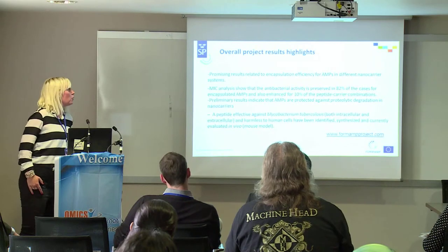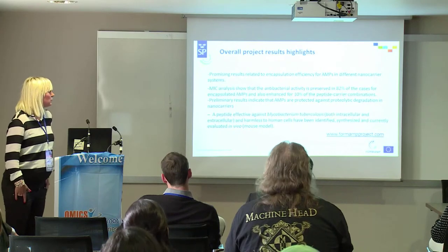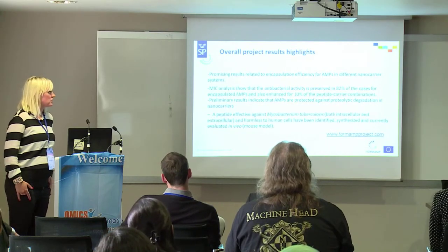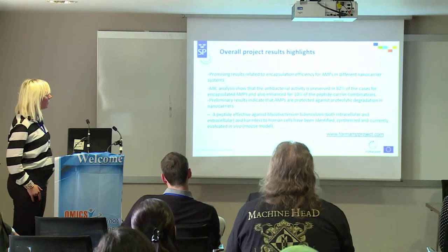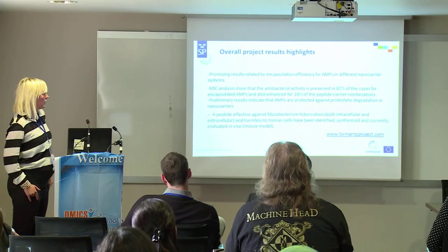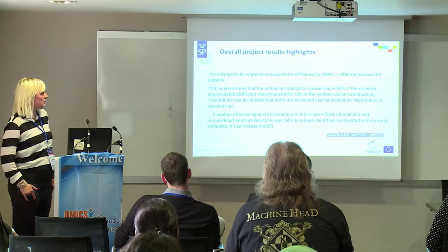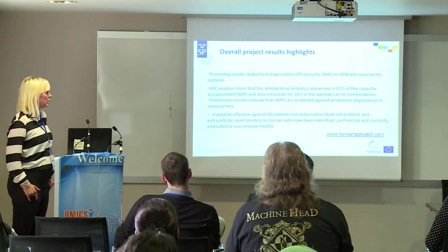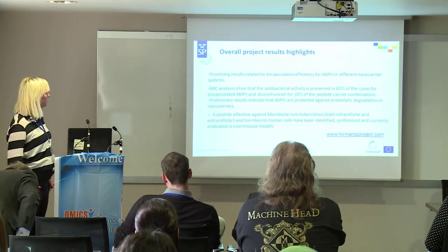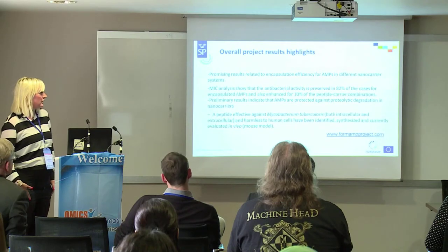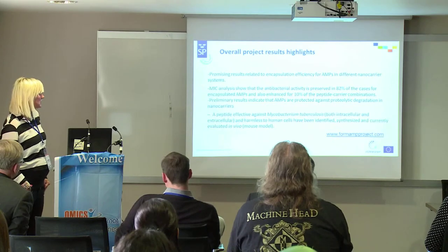So to summarize some overall project highlights up until date, we have seen promising results related to encapsulation efficiency for antimicrobial peptides in different types of nanocarrier systems. By these antibacterial assays, we have seen that the activity is preserved in 82% of the cases, and also enhanced in some cases, which we will look into in more detail. We can also see that the AMPs are protected against proteolytic degradations in these carriers.